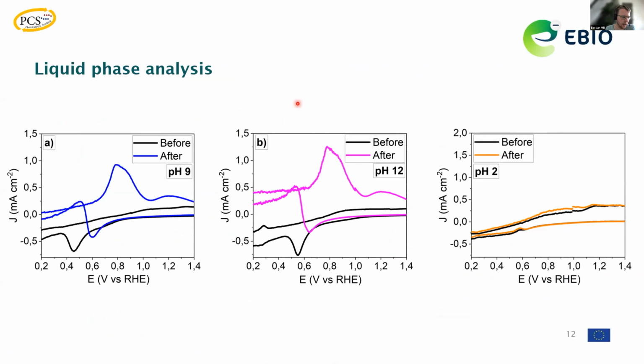But before that, we went for liquid phase analysis, and because we have been using a quite high volume cell of 100 milliliter per minute, the liquid phase analysis by GC didn't tell us anything about any liquid products being formed. But we got a hint that there is actually methanol formation just by doing cyclic voltammetry of the electrolyzed solution after a certain period of time, and you could see that there's certain oxidation peaks that are resembling the oxidation of methanol quite clearly. And you could see that at low pHs, this oxidation peak is not present.